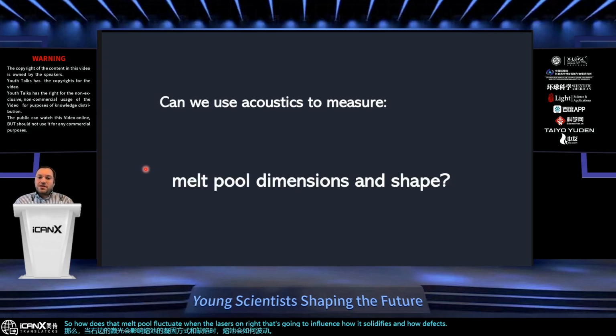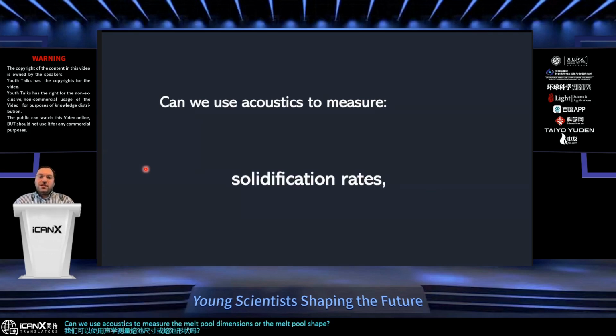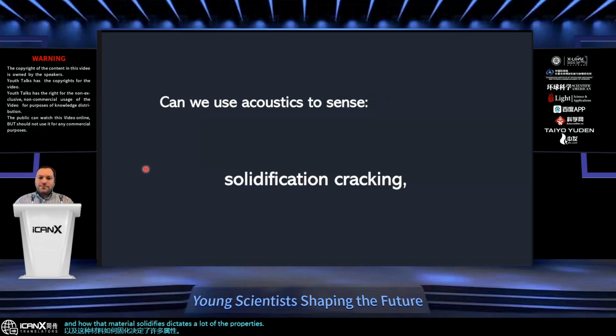Can we use acoustics to measure the melt pool dimensions or the melt pool shape? Can we use acoustics to measure the solidification rate? So the solidification rate is how fast your liquid melt pool solidifies. So think about placing a cup of water in your freezer, you get a solidification front, and that front moves along. And how that material solidifies dictates a lot of the properties.